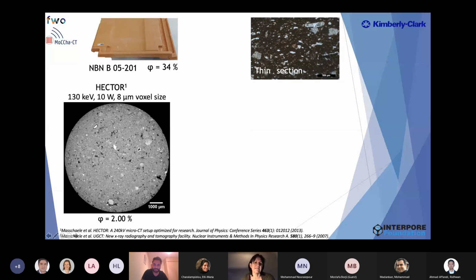So if we scan this with our Hector scanner, one of our scanners, the sample you see here is several millimeters in diameter. Based on what we see as the darker areas, which are the pores, we obtain a 3D porosity value of around 2%.